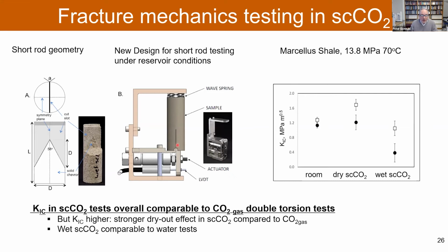But using supercritical CO2, either in very dry form or saturated with water, quite replicates what we do with CO2 gas and water in the double torsion experiment. So the numbers are very comparable, except that dry CO2 dries out the shale rock even more so than the dry CO2 gas. So it's really sucking the water out of the shales, and that increases the fracture toughness even beyond the values that we get in the double torsion test. So dry CO2 has a strong dry-out effect, which increases the fracture toughness. It makes the rock more resistant to fracture, whereas the wet CO2, when it's water saturated, behaves as if the sample were immersed in water.